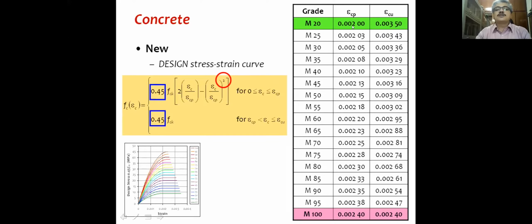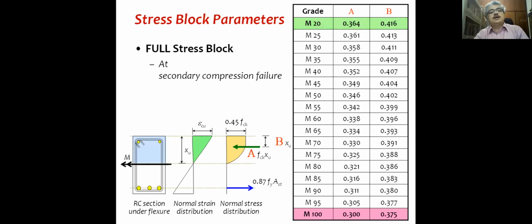So for most of us, we now have to migrate from these fixed values of 0.002 and 0.035 to different values based on grades of concrete. And as Mr. Arora highlighted, at M100, eventually these two values coincide. Now, since the ultimate strain is changing, the stress block parameters would also change. So for all of us who are very familiar with 0.36 fck and 0.42 or 0.416, obviously the stress block parameters are also going to change.